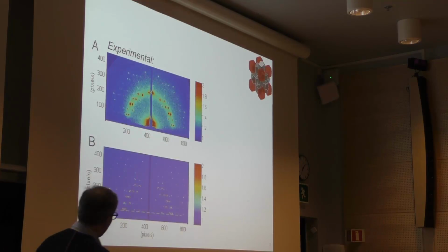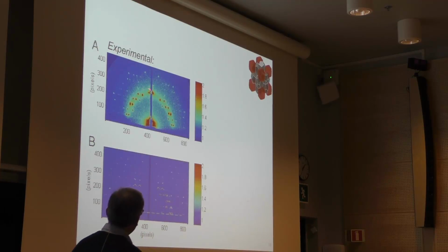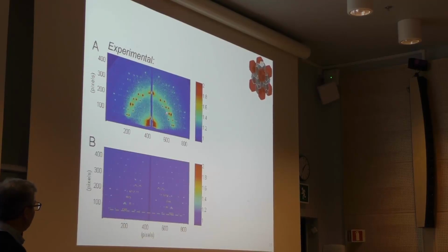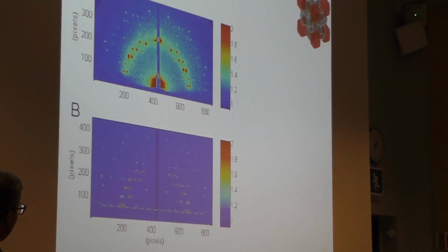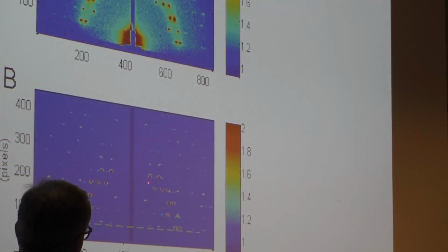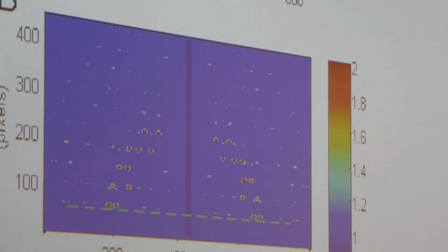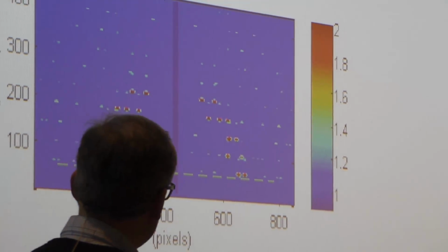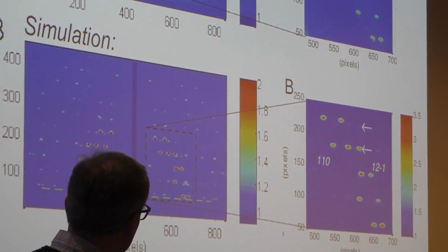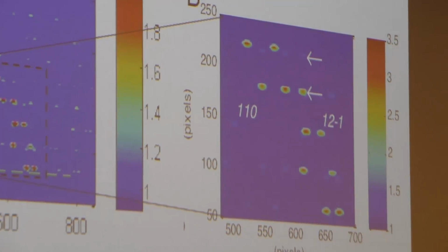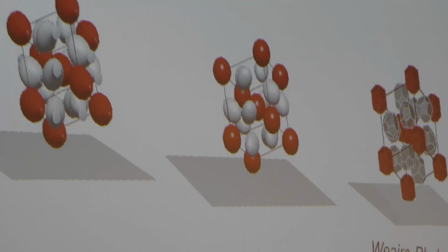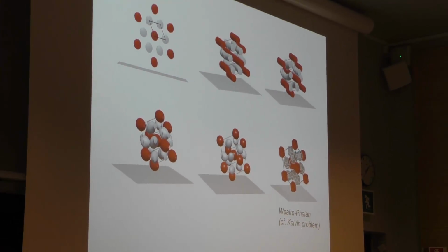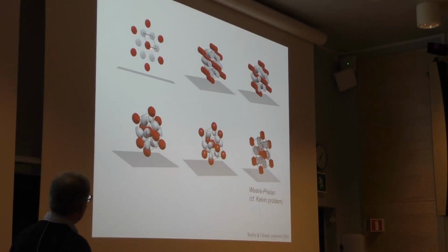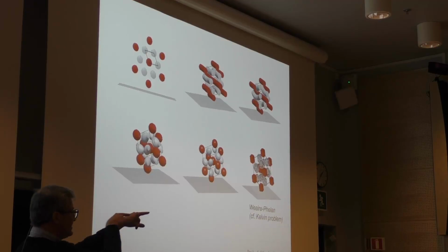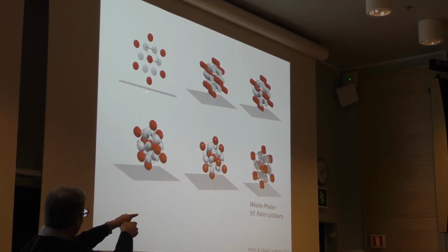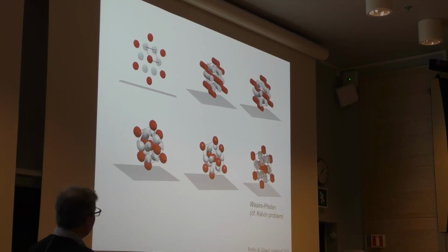So to further emphasize this, this is the last stage of the diffraction pattern that I showed you, and here is a simulation that we have made where you can see that we are capturing all the main diffraction features, giving us full confidence that this is the correct structure. Just to further emphasize this, I'm zooming in here. And here is a cartoon version of what we believe is going on. First we have these cylindrical micelles, in this case seen along their long axis, oriented with respect to a substrate, as you see here.